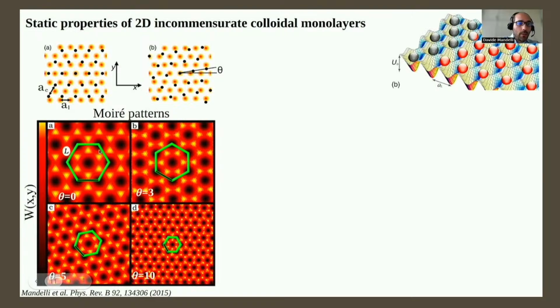What I'm showing here in each panel is a large portion of the colloidal crystal where each particle is colored according to the value of the substrate potential. In particular, black patches correspond to regions of the colloidal crystal where each particle is very close to an energetically favorable region of the substrate potential, corresponding to local minima, while bright patches correspond to regions where colloidal particles are close to the maxima, or energetically unfavorable regions of the substrate potential. The geometry of the Moiré pattern is sensitive to the angular misalignment, and in particular, as we rotate away from the theta equals 0 configuration, the periodicity of the Moiré shrinks, and the Moiré also rotates.